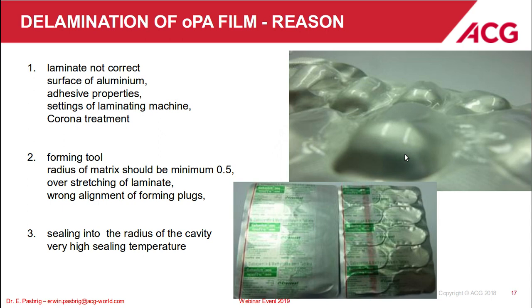There should be the radius of the matrix, so the female part of the forming tool, minimum 0.5. Then overstretching of the laminate will cause delamination. So the cavity should be as safe in the forming as we will describe later. And wrong alignment of forming plugs is one of the main reasons related to delamination. If the plug is not coming in a rectangle into the laminate and forms the cavity, or is shifted so that one side of the cavity is stretched more compared to the other side, the OPA gets more elongated.